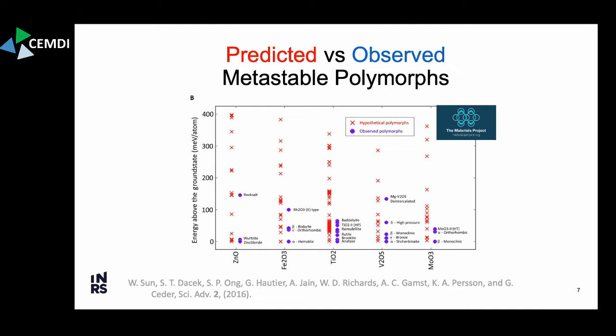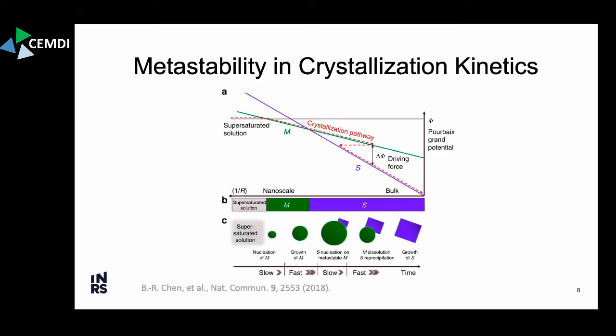So the question is, are we that bad at synthesizing things? You would think, with hundreds of years of modern scientific method and chemistry and development of physics and measurement techniques and characterization, why don't we see this polymorph here, even though we see rock salt, which has a much higher energy above the ground state. So what is really the limiting factor for deciding whether or not we see a polymorph experimentally, compared to its calculated energy? The answer is that beyond just the thermodynamics, you also have to consider the kinetics of how the material crystallizes and evolves through a solid state or phase transition.